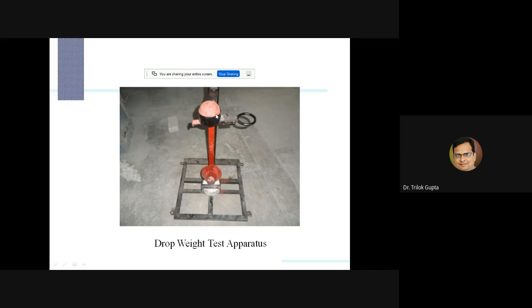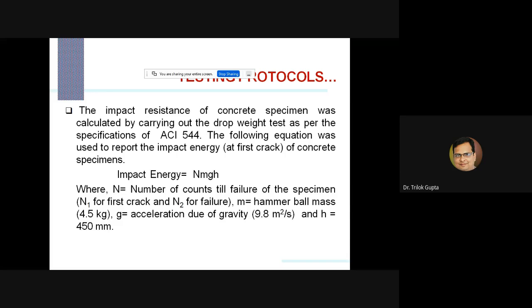So we note down how many blows or falls are required for the first crack as well as the ultimate failure. Means, at the time of a single hairline crack, how many blows or counts are required to develop the initial crack. So that was noted as N1. After that, we continue the testing process and count the number of drops or blows at which the ultimate failure occurs. It will be the breakdown into a number of pieces, meaning more than 2 pieces.